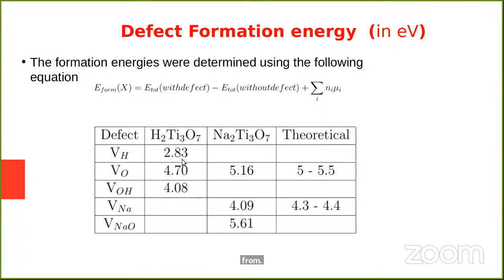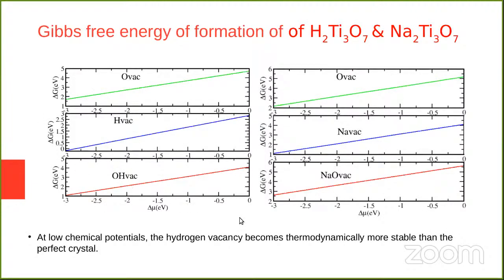From this table, we can see that the hydrogen vacancy and sodium vacancy have the lowest formation energy. And we also consider the thermodynamic stability. The chemical potentials of the relevant species are used to calculate the free energy in the context of ab initio thermodynamics. And we know that at low chemical potential, hydrogen vacancies become thermodynamically more stable than the perfect structure.